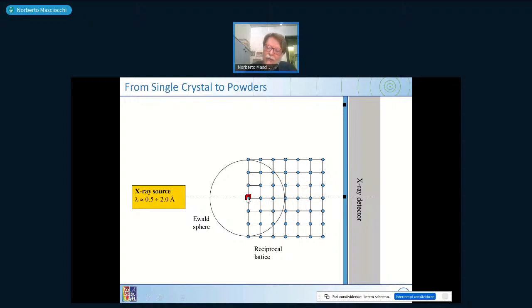Again, we must go back to the idea of shining an X-ray source on a single crystal, and the theory built by Ewald says that there is a so-called reciprocal lattice connected to the real lattice, which is somewhat the condition for having the reflection. So the idea is that when you have a point on this so-called Ewald sphere, then automatically you will have X-ray light scattering. So for example, if you take this point and you see it's nearly on the surface, you have light shining in this direction. And so this spot is created automatically by the positioning of the sample.